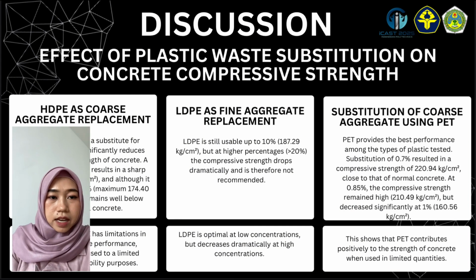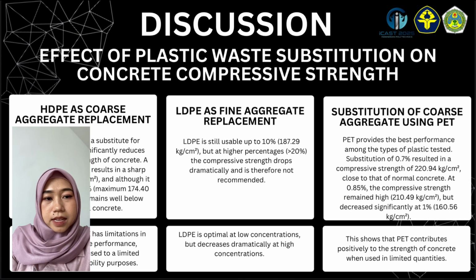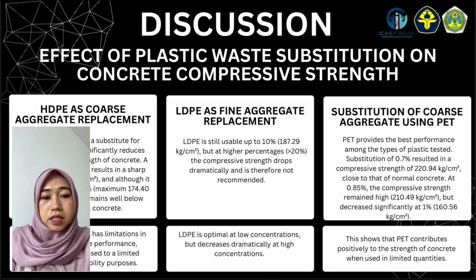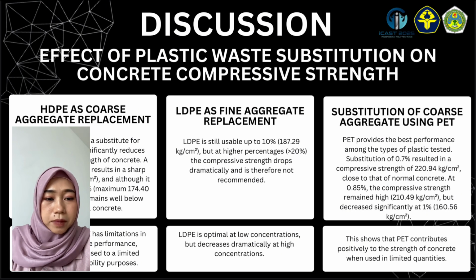Substitution of coarse aggregate using PET. PET provides the best performance among the types of plastic tested. Substitution of 0.7% resulted in a compressive strength of 220.94 kg per square centimeter, close to that of normal concrete. At 0.85%, the compressive strength remained high but decreased significantly at 1%. This shows that PET contributes positively to the strength of concrete when used in limited quantities.